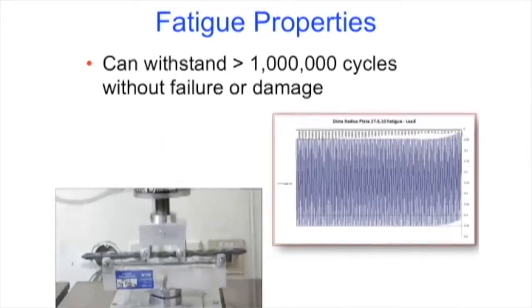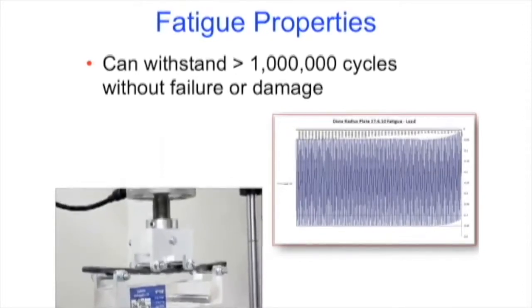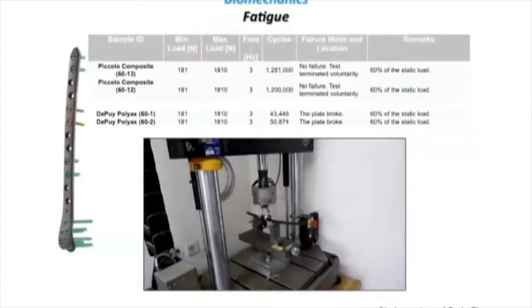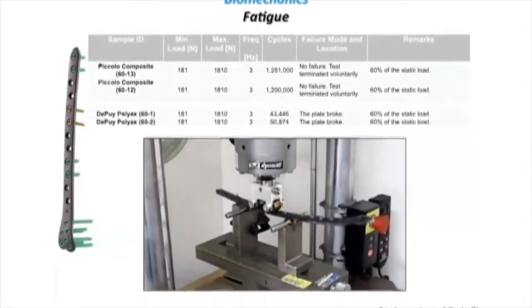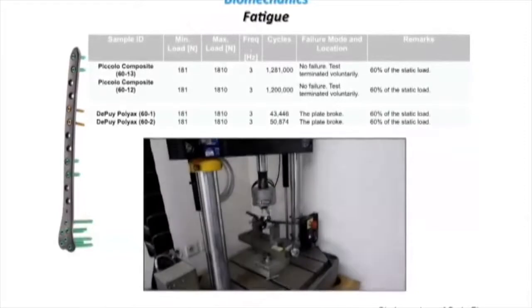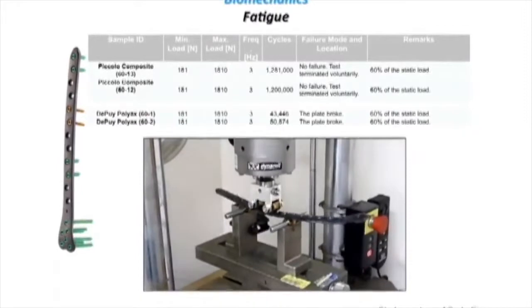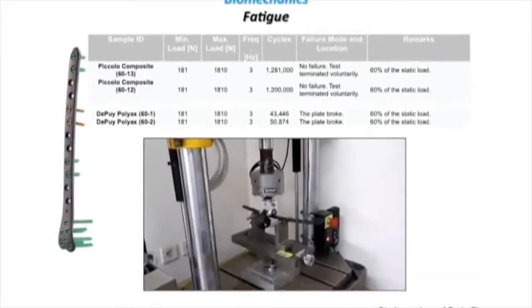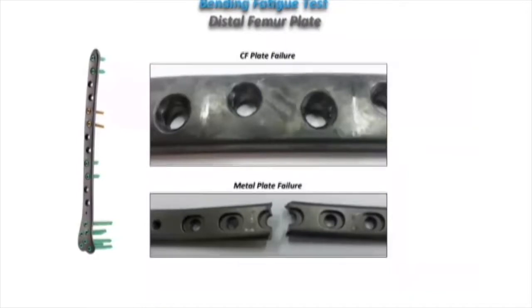So as John said before, they did a lot of four-point bending tests, and you can see that it actually generates a very favorable profile in terms of fatigue. You could stand 1 million cycles without failure or damage. Not only that, though, but you can also see that the strength and the strain of it is also much more favorable than a metal. This was a study that was sponsored by CarboFix, and you see they compared their carbon fiber implants to a DePuy Polyax plate. And you see here that both of them, within 60% of their static load, had a better load to failure and a maximum load to failure as compared to metal, okay? Where the plate broke, but in carbon fiber, it did not. And so this was pretty amazing.